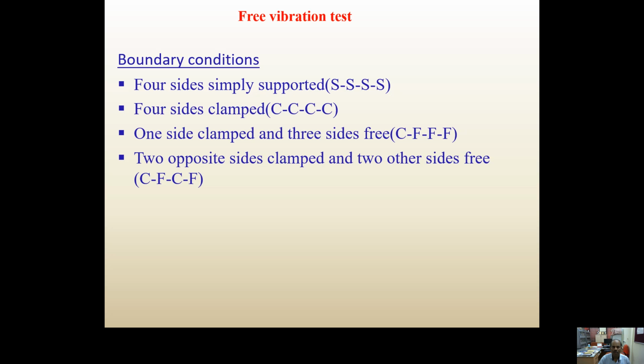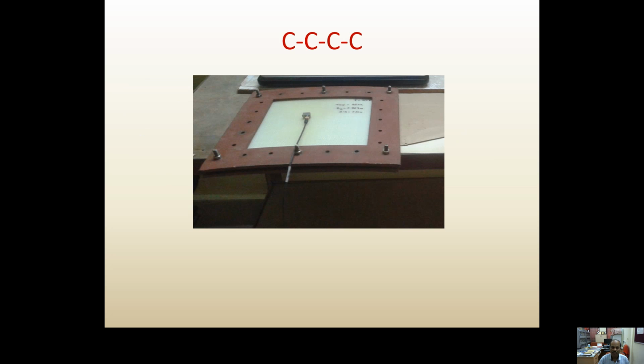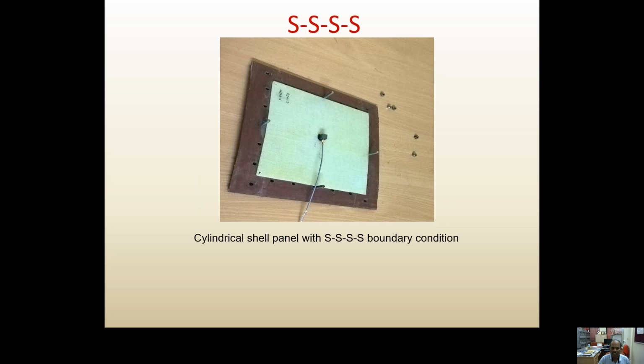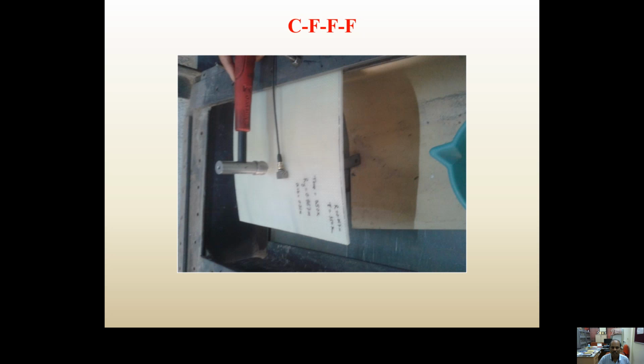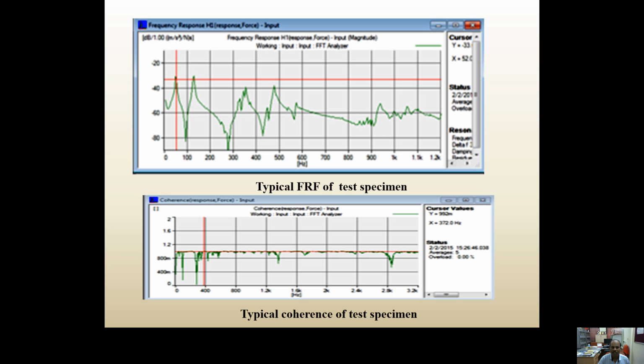The boundary conditions for the free vibration test: 4 sides simply supported, 4 sides clamped, 1 side clamped and 3 sides free, that is cantilever, and 2 opposite sides clamped and 2 other sides free. These are the boundary conditions considered. So this is a fully clamped shell specimen subjected to hydrothermal loading. This is the cylindrical shell specimen with simply supported boundary conditions subjected to hydrothermal loading. This is the cantilever specimen. This is a typical FRF showing the frequency response spectrum and the corresponding coherence curve showing the accuracy of the measurement.